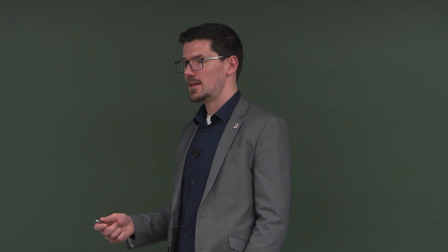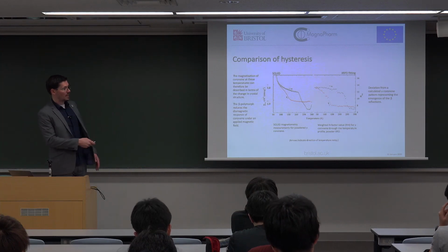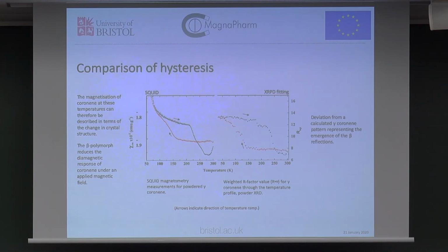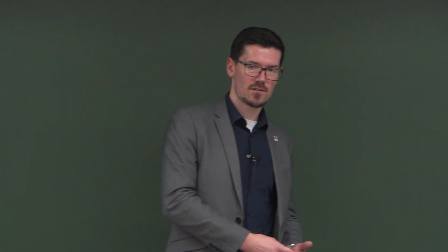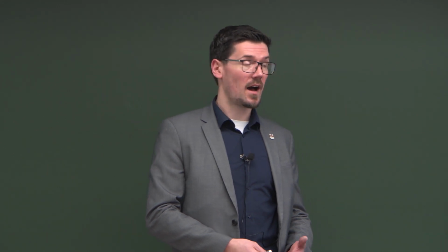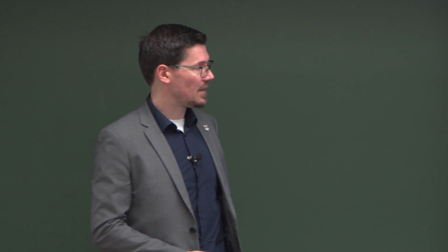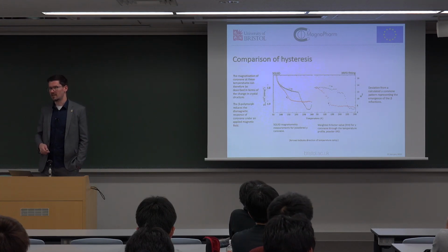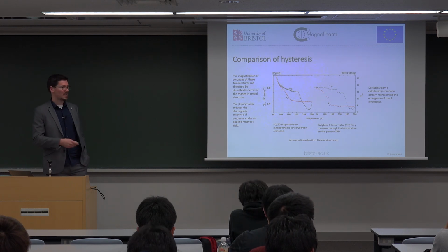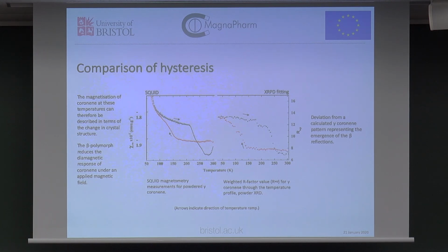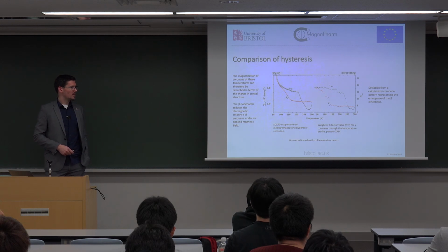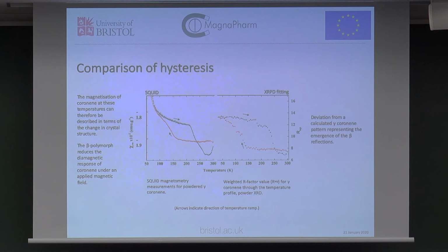Can we match that to the hysteresis we see in the structural analysis with the X-ray diffraction? Yes, we can. So on the right, these points, I've colored them to look the same as the SQUID data, but basically I've done Rietveld refinement on each of the powder patterns that we generated in that low temperature data. But I've refined it to the gamma coronene structure. So the more we deviate from the gamma coronene structure, the higher the R value is going to be. So I'm not catering for the beta coronene in this analysis, basically to show a deviation away from gamma coronene and try and get some feel for how much we can see this. And you can see the hysteresis follows the SQUID data almost perfectly. It doesn't quite go as low here, but it's a really, really good comparison between the two. This wasn't exactly the same sample, so the fact that the crossover is in a different place likely just means I had slightly different crystallite sizes.